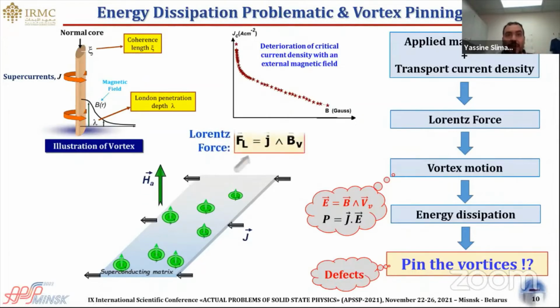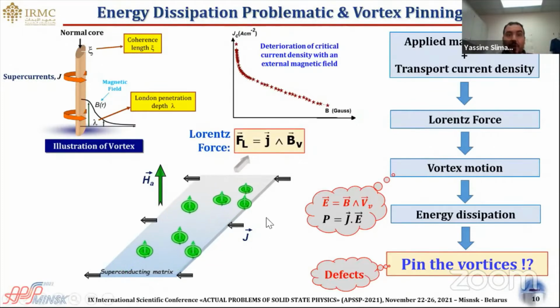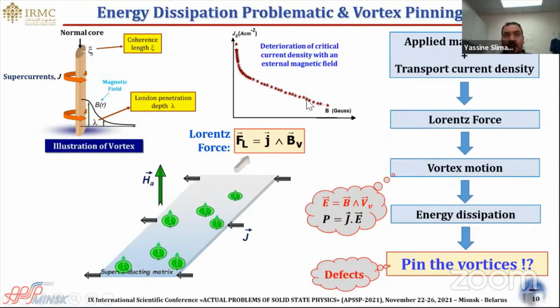Under the effect of an applied magnetic field and in the presence of a transport current density, a Lorentz volume force will be applied on the vortices. This force will put the vortices in motion, which induces a non-zero resistivity and consequently a dissipation of energy. So once we measure the critical current density versus the applied magnetic field, we find that it decreases rapidly with increasing intensity of the applied magnetic field.